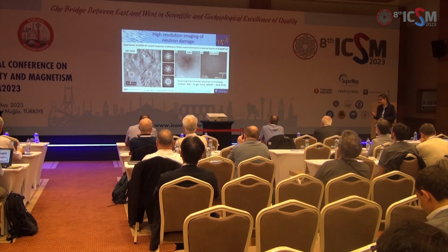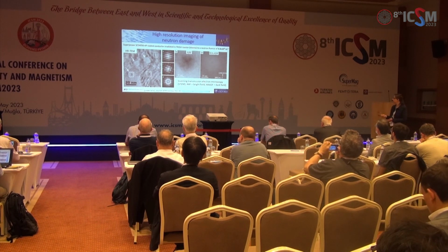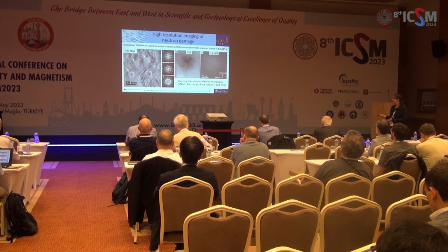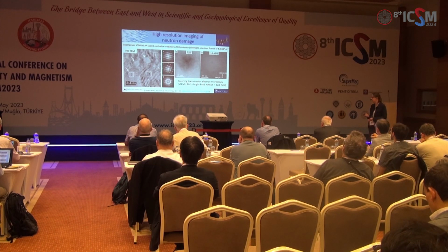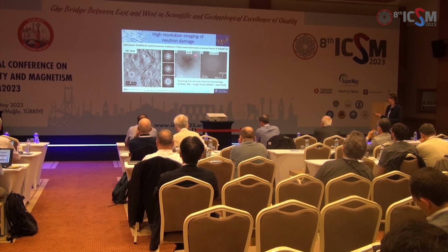We can see them in the TEM. So this is a microscopy done by one of my DPhil students. Here are the kind of features that are those amorphous regions that are caused by these damage cascades. You can see them in other imaging modes as well in the STEM. It depends which imaging mode we're looking at. Here's one of them here in a bright field image.